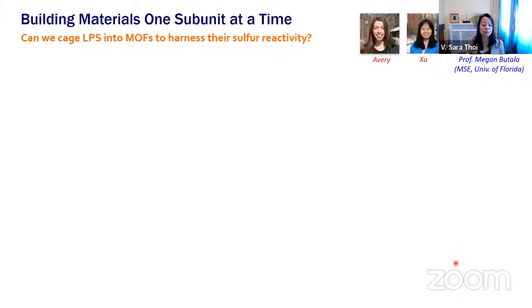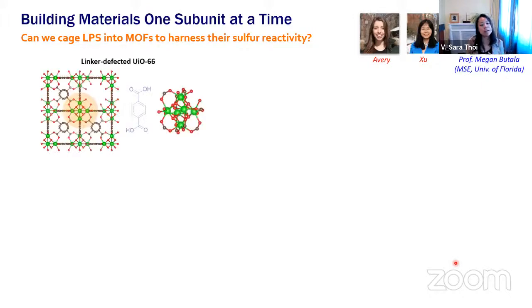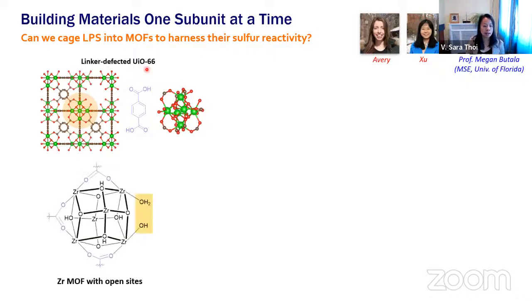Lucky for us, metal organic frameworks are excellent materials for protecting things from reactivity. And so we took a pretty canonical metal organic framework called UiO-66, which is composed of these hexanuclear zirconium clusters that bind to this benzene dicarboxylate linker that I've already shown before. In addition to that, we punched some holes into this beautiful framework by removing some of these organic linkers, to what is called the linker-defected UiO-66. If I zoom into a ChemDraw picture of what a zirconium cluster looks like, you see that the zirconium cluster is bridged by these hydroxides. And by punching out some of those organic linkers, we get terminal sites where there's a hydroxide and a water molecule bound to the zirconium.